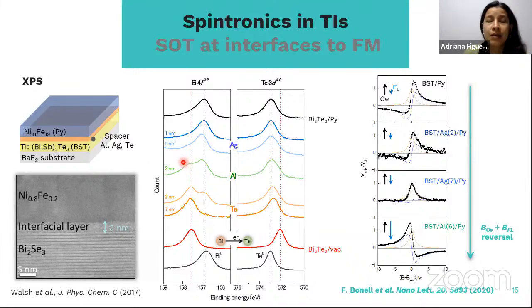And that happens mostly with aluminum and also with tellurium, but tellurium is not a good material to use in spintronic applications in this case, because tellurium is a very good spin absorber, and we don't want the tellurium to absorb all the spins that are accumulated on the TI. We want those spins to go through the permalloy and then exert a torque on the permalloy, and do some switching of the magnetization and so on. So in that case, we observe that the optimum material to be used here is aluminum of about 6 nanometers. So this is the best, the optimized result that we got.